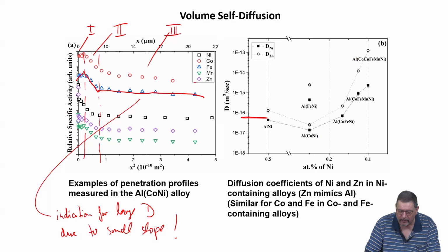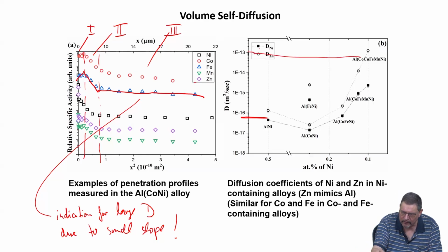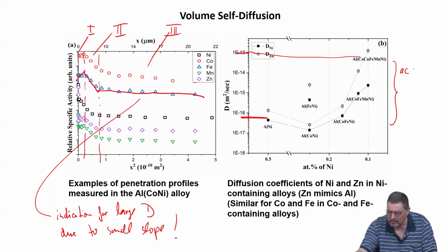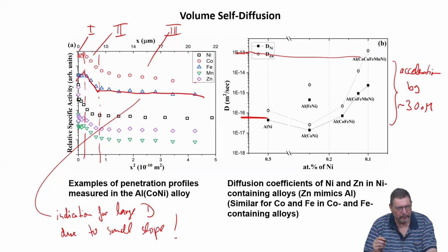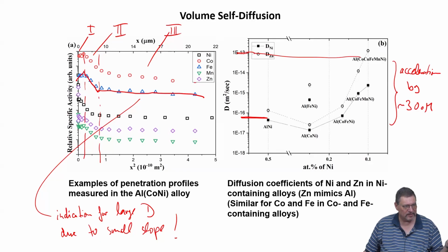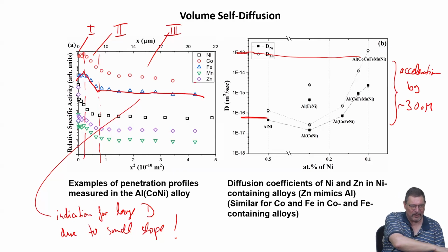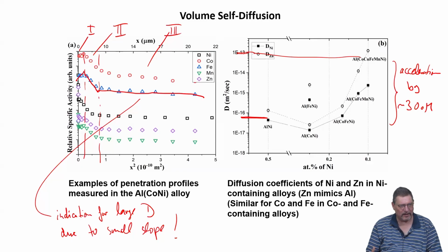So we are here at a level of about 10 to the minus 16, and we are here at a level of 10 to the minus 13. So this is acceleration by roughly 3 orders of magnitude, going the wrong way, going from rather pure sublattice to high entropy sublattice. And that's very interesting, because we see that sublattice high entropy alloy design makes diffusion significantly faster. 3 orders of magnitude difference is much more than almost any high entropy effect in the other alloys has caused in terms of deceleration of diffusion. So the anti-sluggish diffusion effect in these aluminides is stronger than the sluggish diffusion effect in all the other high entropy systems we have studied.